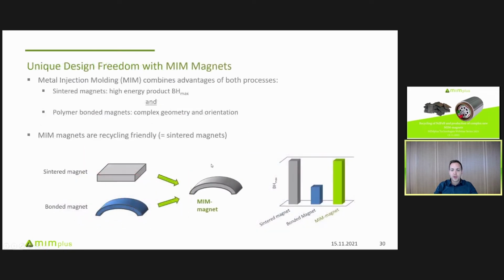Now we come into the game with the metal injection molding process. It combines the sintered magnet route with the polymer bonded magnet route to produce sintered magnets with a complexity that is only known so far from bonded magnets. It means the energy product and the magnetic properties are the same as for sintered magnets, but the complexity is much, much higher. And also the orientation of the magnets can be realized with higher freedom.